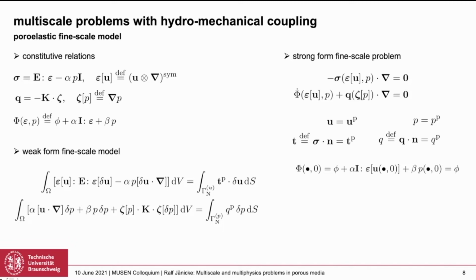But okay, in poroelasticity, we have typically a stress which is defined as a solid contribution from linear elasticity and a fluid or pore pressure contribution, where alpha is a Biot parameter somehow representing the compressibility of the fluid. Here, typically that's water, and even though water is widely assumed to be incompressible, here we have to consider it to be compressible because the compressibility of water is in the same order of magnitude as the inverse bulk modulus of the solid grains and the rock.